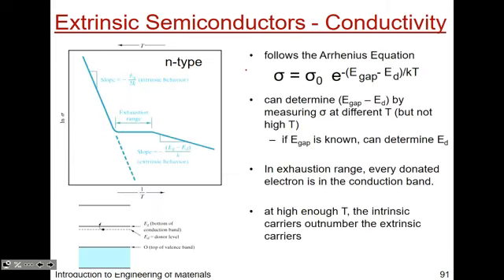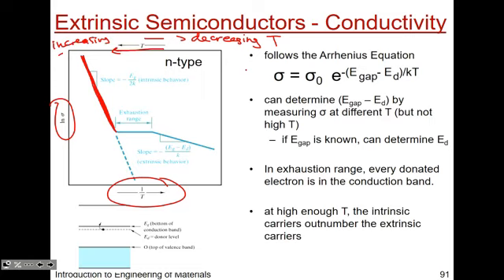Okay, so how does your doping affect the overall conductivity? Well, depending on if it's N-type or P-type, you have different relationships. So here you see the log of the conductivity as a function of reciprocal temperature. If you just had intrinsic behavior, what we saw before, this thermally activated process, we see this regime where the slope is just your band gap divided by 2 times Boltzmann's constant. But if you go this way, you're decreasing temperature. If you go this way, obviously, increasing temperature.